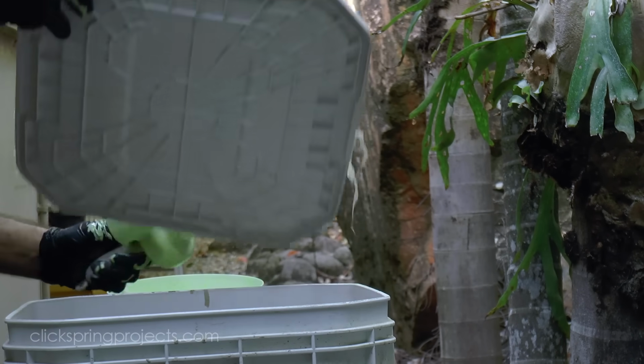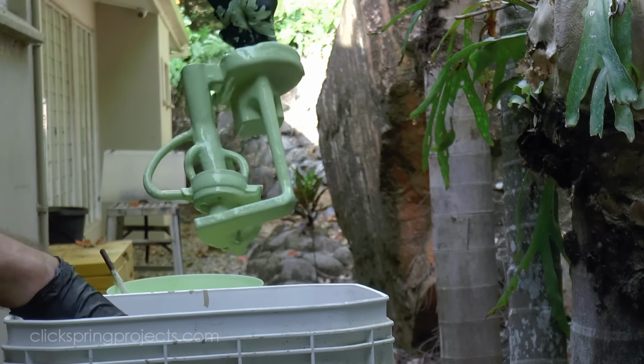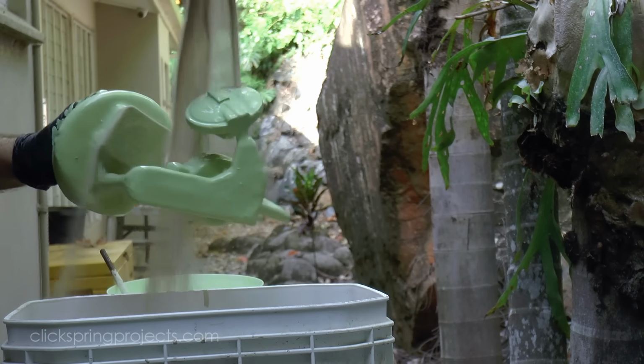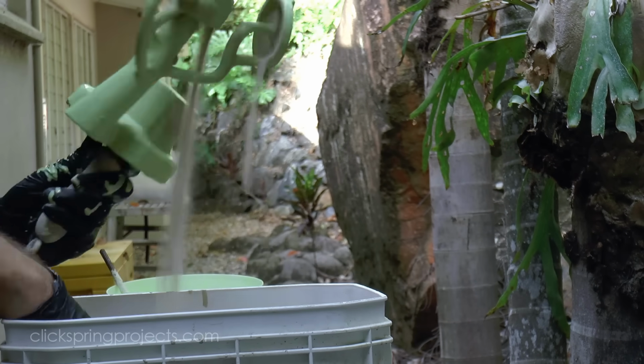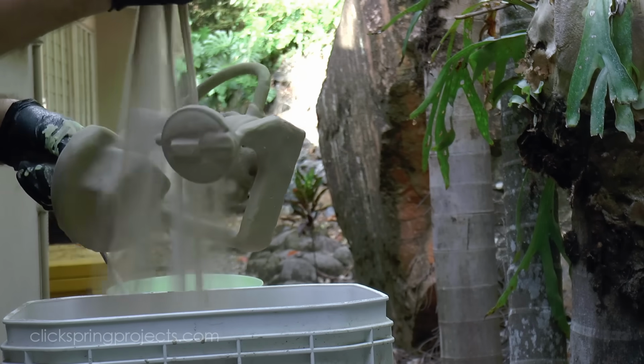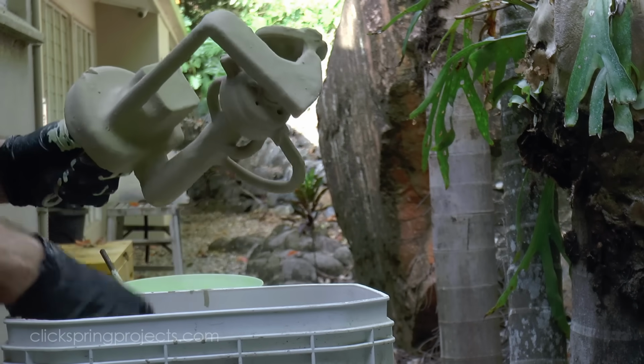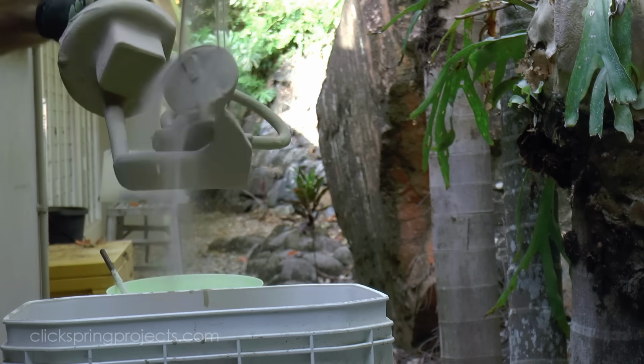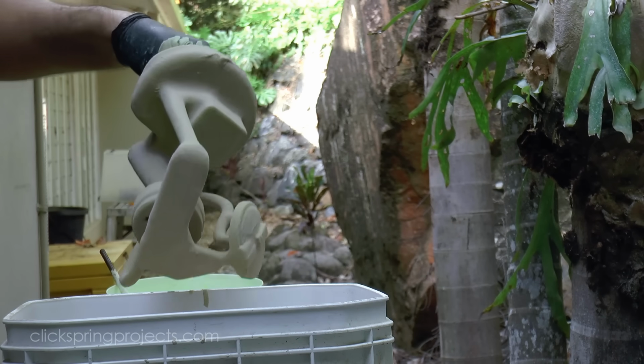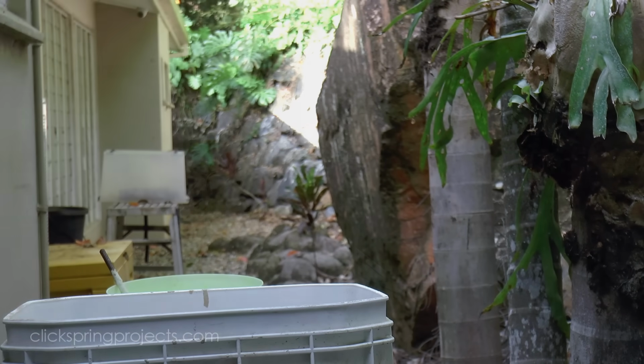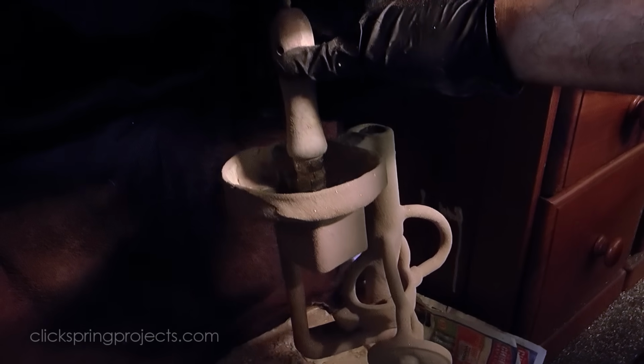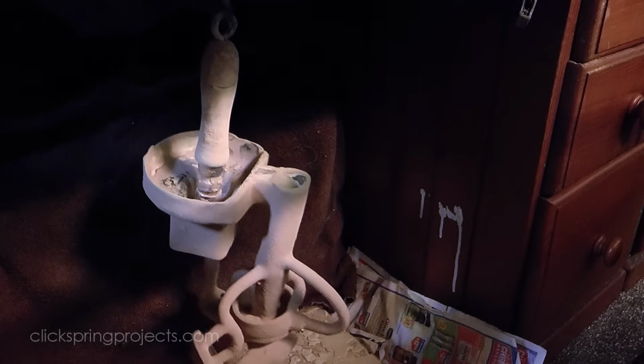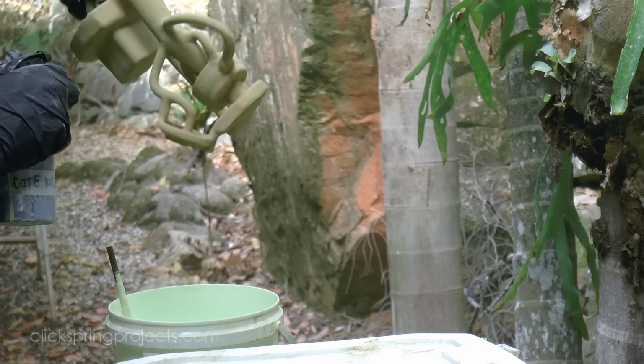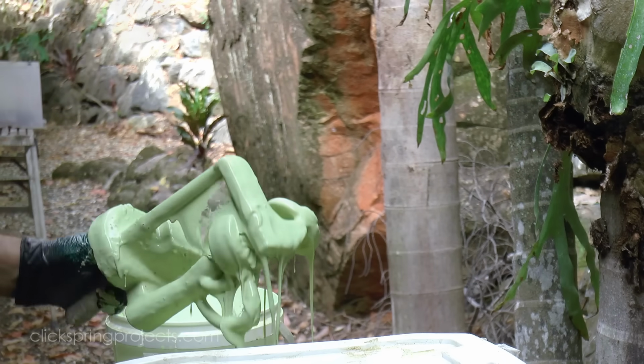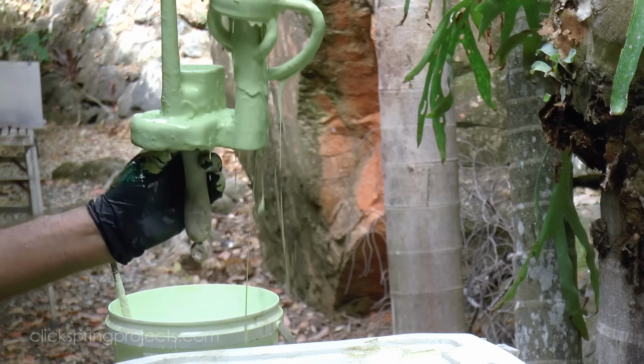Now, I mentioned earlier that the prime coat binder has a dryness indicator, which is the source of the lime green colour. Fully wet is green, but as the material starts to dry, it'll turn a light orange, and after enough time, a pale yellowy white. For subsequent layers, this dryness indicator can help to confirm how well the material is drying, but generally I tend to allow 4 to 5 hours for each subsequent layer to dry. So after that first coat, I can generally get in 2 complete cycles per day from then on.